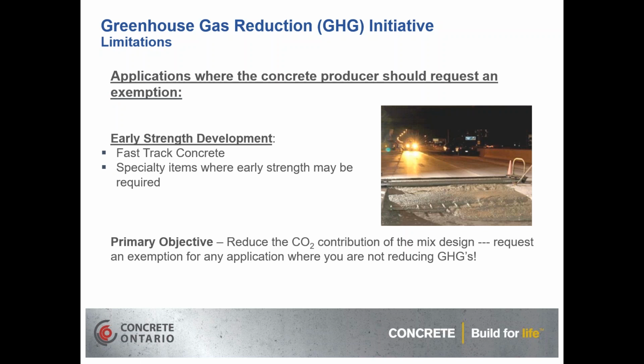So some applications where the concrete producer should request an exemption. Again, we're looking at those early strength development type projects where we're looking at 4 hours, 6 hours, 8 hours to open it back up, wanting to hit 15, 20, 25 MPa in a short time frame, or other early strength mixes. But what you want to do is try to reduce the CO2 contribution of the mix design and request an exemption for those applications where you're not necessarily realistically able to reduce the greenhouse gases.